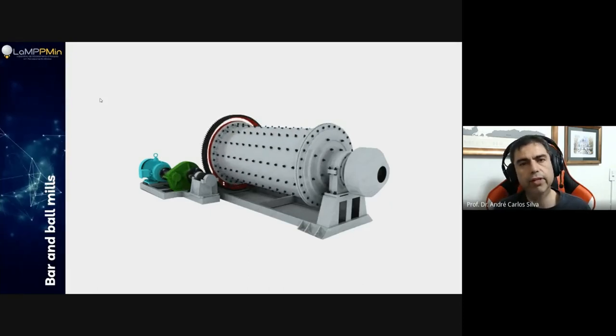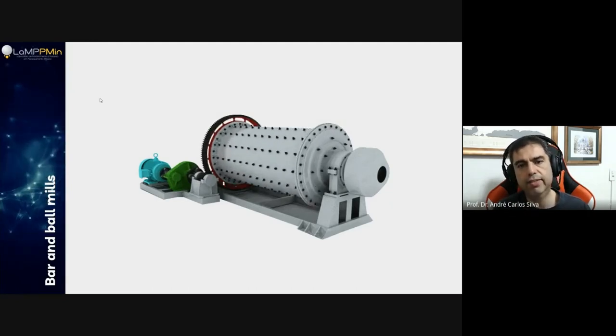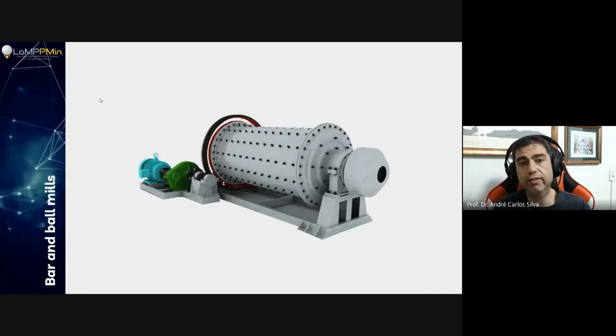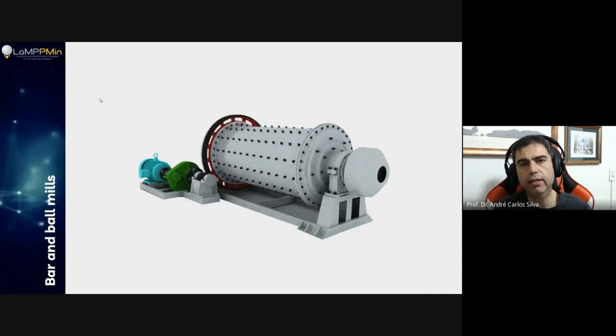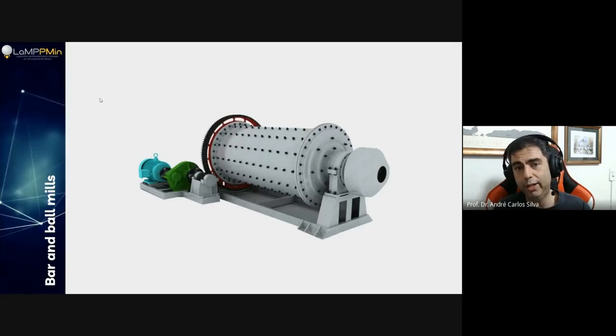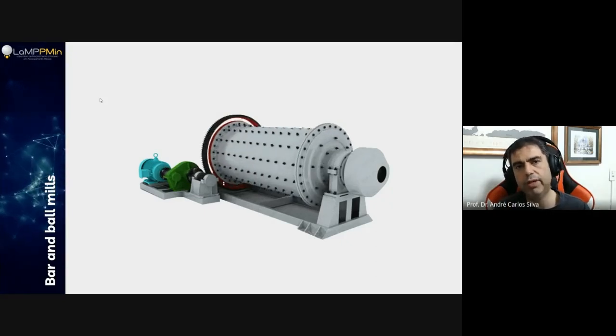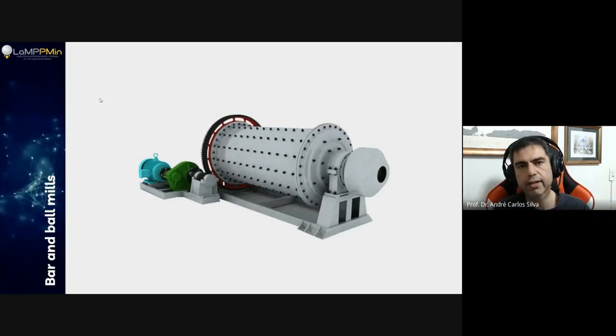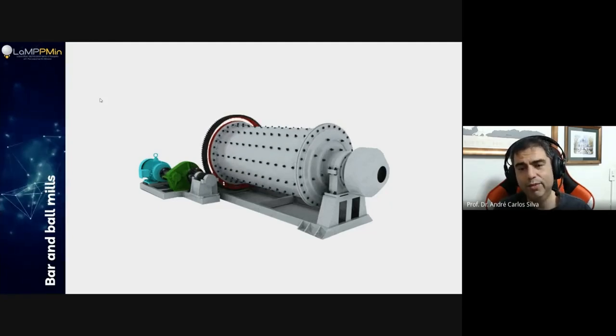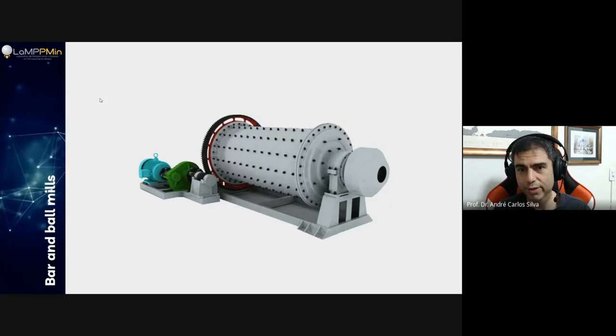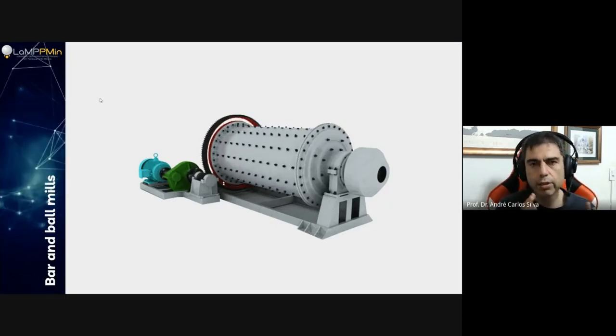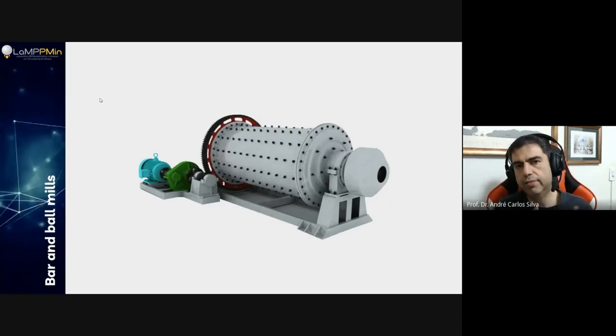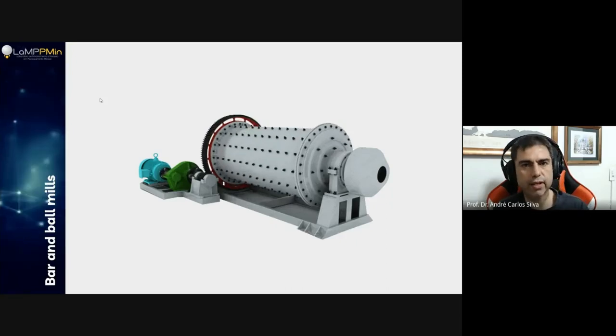So you avoid at all costs having different sizes of bars, because otherwise the bars can start to mix together and even fuse together, and then you lose all of your load in the mill. You have to stop the mill and cut the bars out of the mill. So it takes a lot of energy and time to reclaim this material from your mill. So again, try to use, as much as you can, bars the same size as the mill.